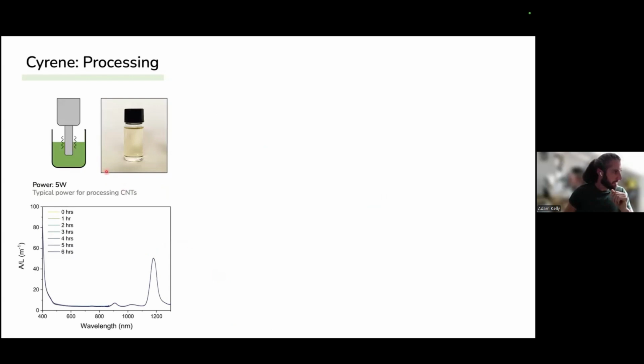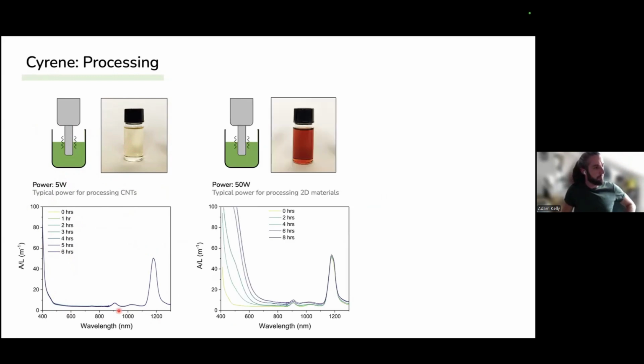So typical powers for the sonic tip for processing carbon nanotubes are about 5 watts. So we processed just pure cyrene at 5 watts for up to 6 hours just to make sure we weren't seeing any changes in the solvent. And at 5 watts, these are UV-vis spectra, there are no changes. If we sonicate the pure solvent at 50 watts, which is a typical power that you use for processing 2D materials, what we see is drastic changes, particularly in the visible part of the spectrum, where for processing times up to 8 hours, which is a pretty common processing time, almost the entire spectrum from 600 nanometers downwards is now dominated by what we've created in here, this degradation product.